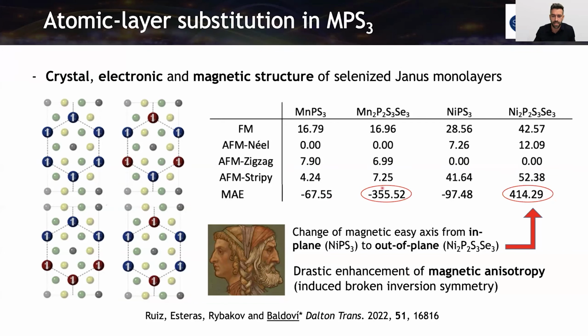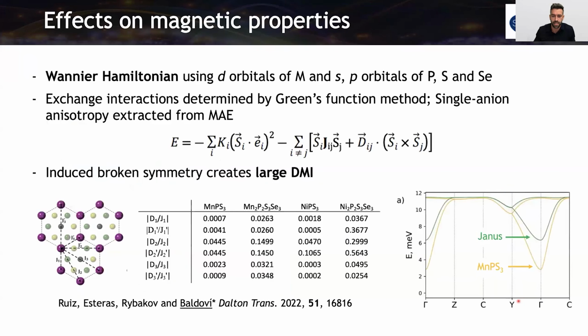You can see here that it's very enhanced. And also there's a change in the sign here, so from this to this. Now in this case, this means that the nickel is in plane, and in the case of the Janus nickel PS3 with selenium it is out of plane. So this is a drastic enhancement of magnetic anisotropy, and also this possibility of changing from in plane to out of plane. Then we go to the Wannier Hamiltonian.